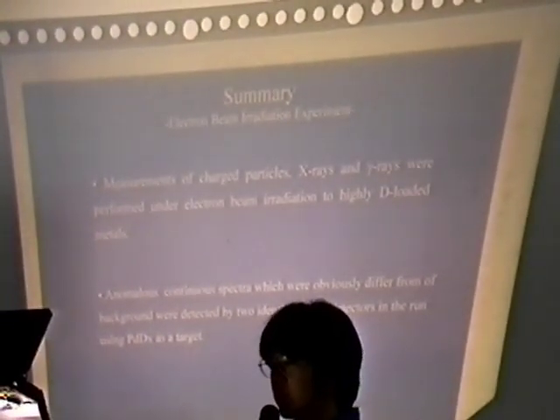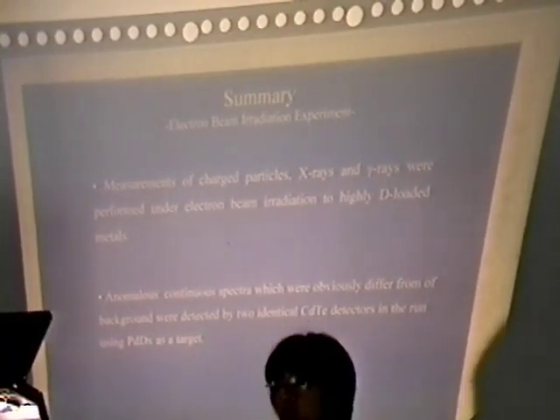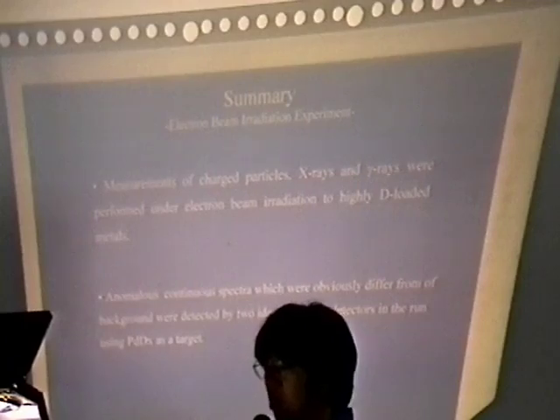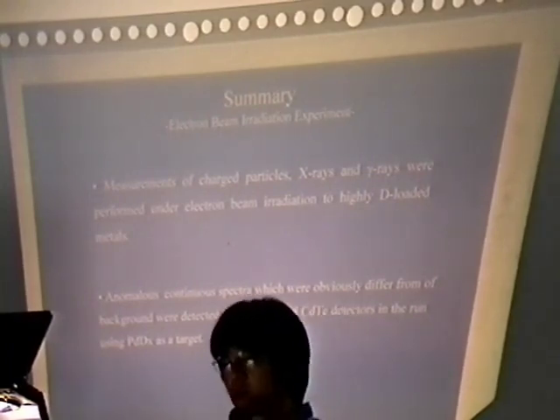Therefore, there is every possibility that these spectra are due to a tail of a Compton continuum or continuous X-rays by slowing down of charged particles. But of course, to confirm this assumption, further experiments are necessary. Short summary of this experiment. Measurements of charged particle X-rays and gamma rays are performed under electron beam radiation to highly D-loaded metals. Anomalous continuous spectra, which were obviously different from background, were detected by 2 identical cadmium telluride detectors in the run using PdDx as a target.